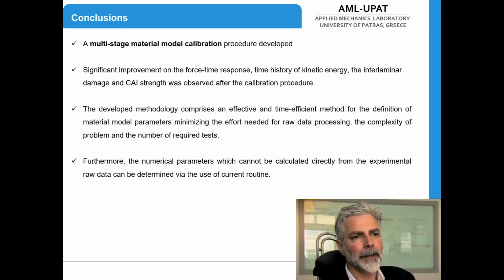As concluding remarks, we may say that in this work we propose a multi-stage material calibration model that can be used for the simulation of impact tests. It is at the level of the energies that we try in this work. The results were very promising. Not only the delamination area, not only the peak load, but also the behavior of compression after impact was captured